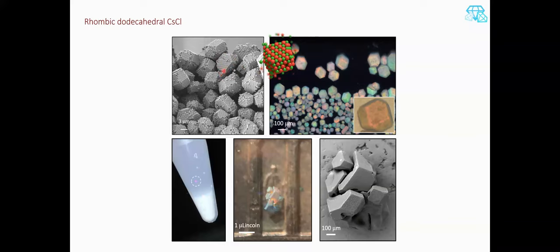So, this habit, these are relatively small crystallites of 5 or 10 microns, but that habit persists through 100 micron crystals, even up to a millimeter, and so this crystal, in particular, demonstrates what can be done with relative ease, which is that we just shake up oppositely charged particles with some soap and salt, and some of the crystals grow to enormous size. I think here the trick was that a nucleation event stuck to the side of the vial while the rest sedimented, and then it didn't crowd up with all the other crystals and was able to just consume particles and grow for a few days, and so then we're left with this, you know, macroscopic object. We can see this is on the back of a penny, and just once again, these rhombic dodecahedral shapes are present, and if we look closely at each of these planes, we're not going to see them because we're so zoomed out, but if we look closely at each of these planes, it's again, it's the 110, so we get well-defined habit across length scales.